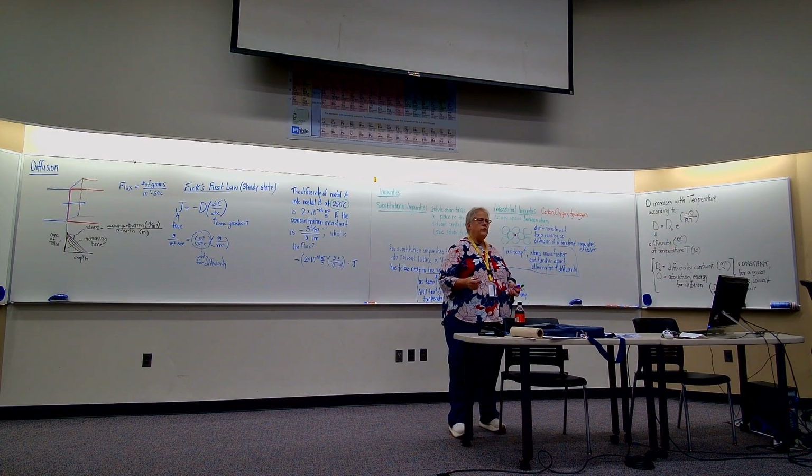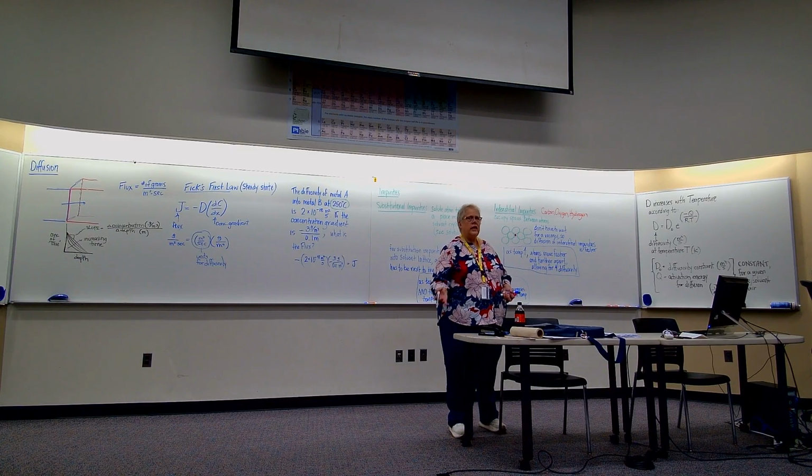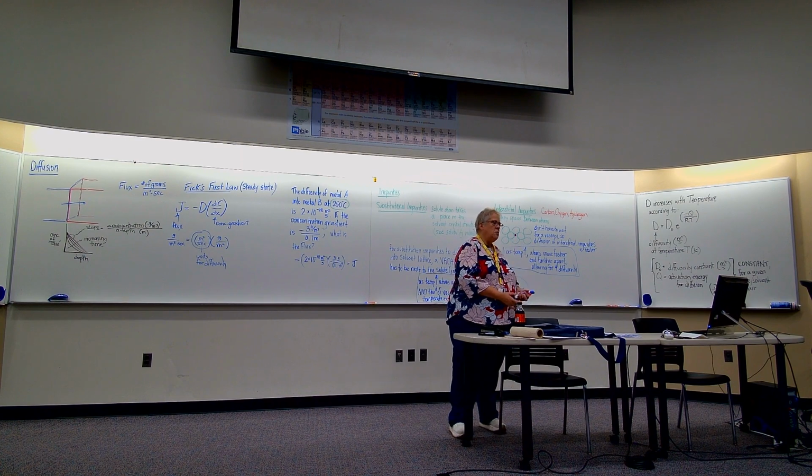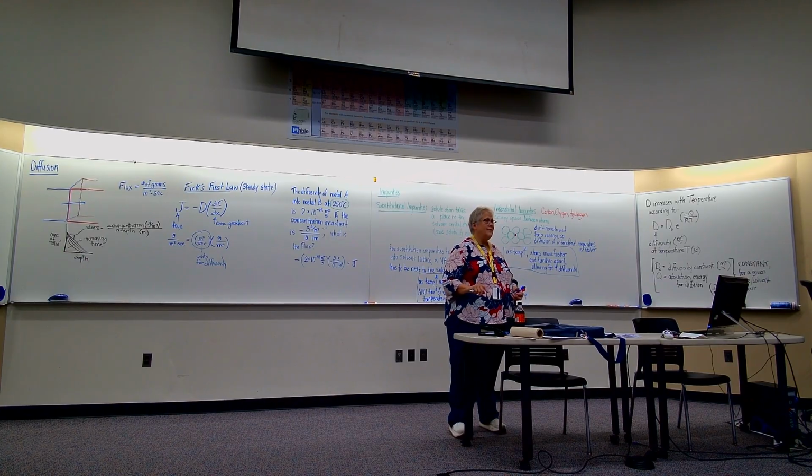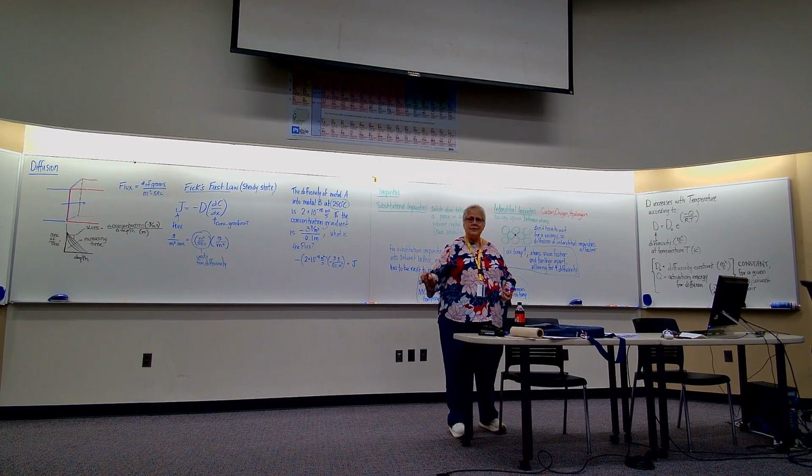So the value of Q and D0 is unique for nickel diffusing in, what did we say? Nickel, copper? Nickel, copper, yeah. So nickel in copper has a unique Q and D0. Copper in nickel has a different Q and D0.